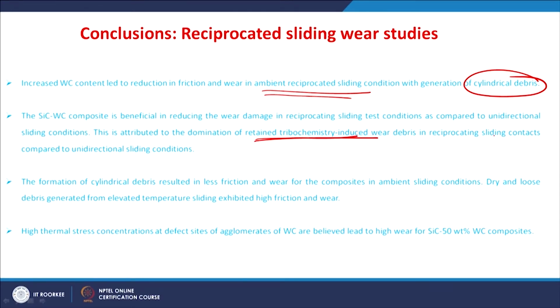The formation of this cylindrical debris resulted in lesser friction and wear for the composites in the ambient sliding conditions, whereas dry and loose debris generated from the elevated temperature sliding conditions resulted in high friction and wear. So, high thermal stress concentration at the defect sites of the agglomerates of tungsten carbide particles is believed to lead to higher wear when there is a larger amount of tungsten carbide content.